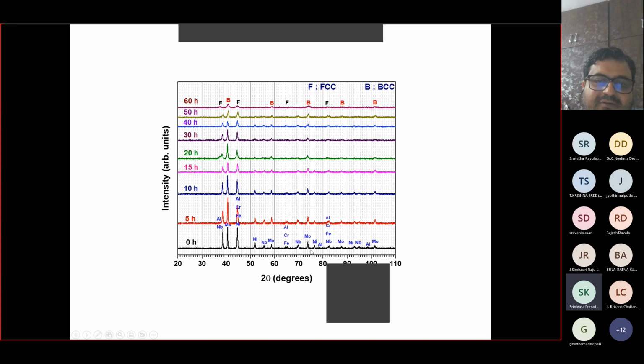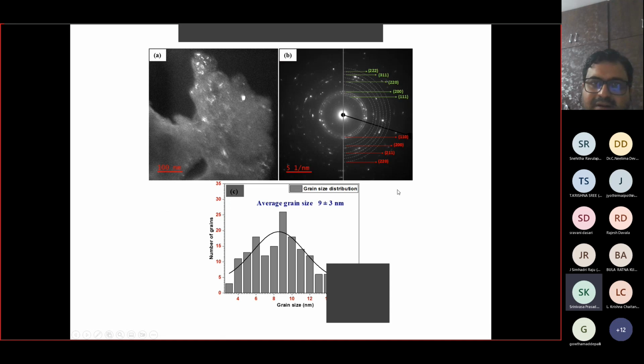You see here, in the beginning of the milling, we have the presence of all the peaks of all the elements. But as you increase the milling up to 60 hours, you form a two-phase structure, an FCC and a BCC. BCC is the dominant phase and FCC is the minor phase. And the transmission electron microscopy and other studies show that we have a two-phase structure clearly coming from BCC and FCC, and the grain size is about 9 nanometers. It's extremely fine.